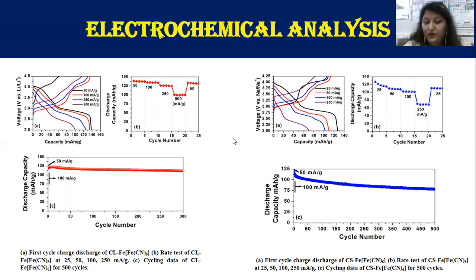delivered was 127 at 25 specific current, and at 250 specific current the capacity was 70 mAh per gram. When the electrode was cycled back again to 25 mA per gram, it could still maintain a capacity of 110 mAh per gram. So at a higher current density of 250 mA per gram, the capacity decreased. However, as a future perspective, the capacity can be improved by a conducting additive.